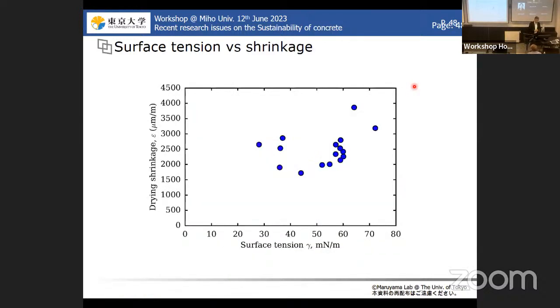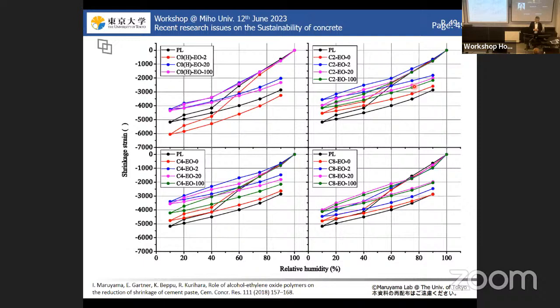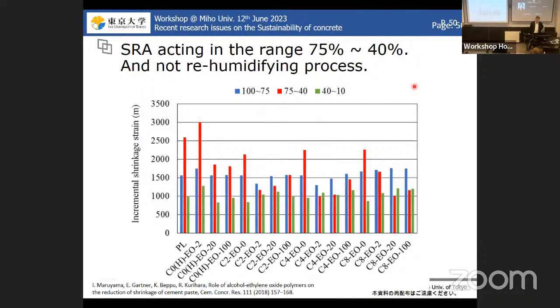But if we plot the drying shrinkage of hardened cement paste against the surface tension of the pore solution, actually there is no correlation. So this suggests that the reduction of the surface tension of the pore solution is not the dominating factor in the reduction of the shrinkage. This has been discussed for a long period, and I confirmed it experimentally. And I also measured the hysteresis loops of each hardened cement paste, and I summarized the experimental data here.